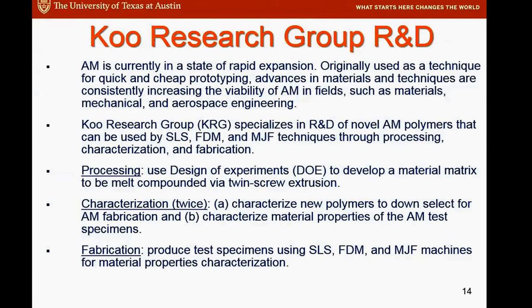And that's how we come up with, we use design of experiments, always use twin screw extrusion to actually come up with the formulation. And we characterize it twice. First, we actually were able to down select. I'll show you some example. You may have a matrix of 12 materials. Well, you cannot make all these materials. You need to down select in order to make actually a fabrication. So that's what we are using. First, down select the polymer with these different compositions, and later on, print it. We'll use the same technique, and that's what I'm going to talk about.